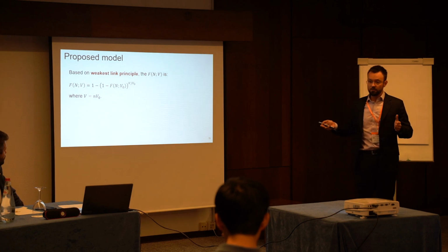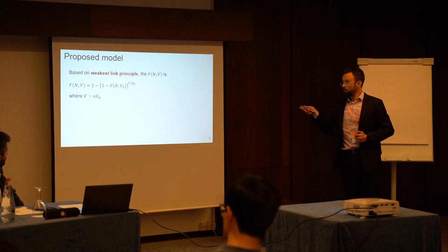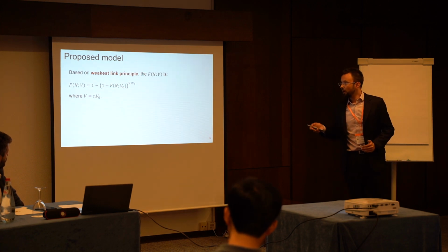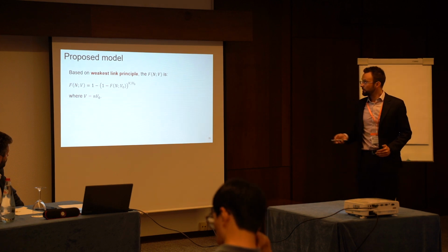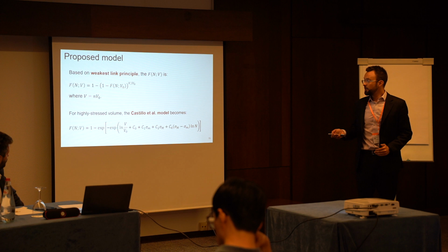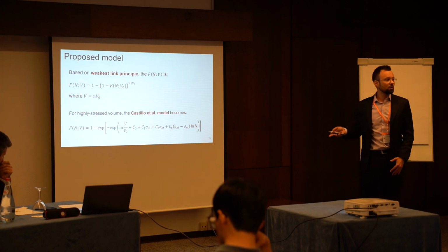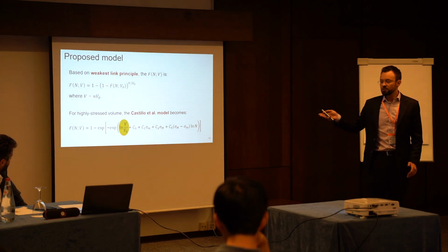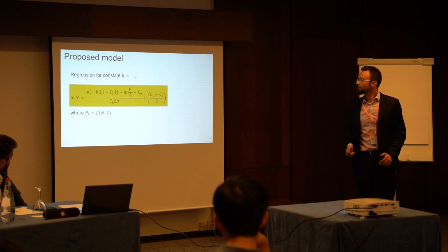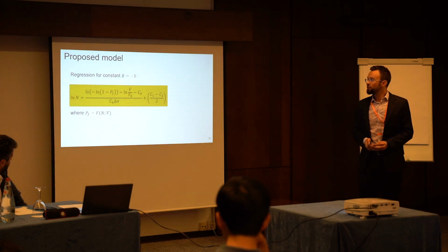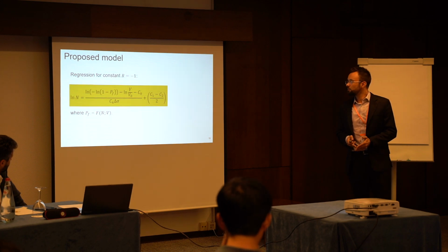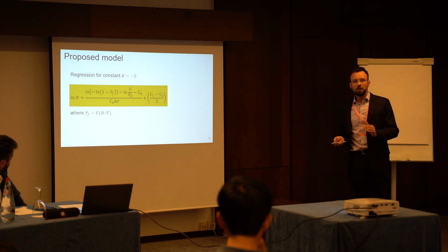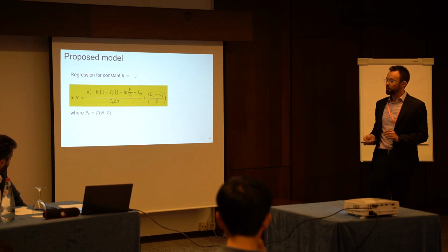As in the Castillo model, this model is based on the weakest link principle, and here is the relation between smaller and larger volumes. And here, for highly stressed volume, the Castillo model becomes this one. It's interesting that the main difference is there. Here is the regression equation for constant ratio, minimum and maximum. And we also obtain similar regression equations for the case of surface.